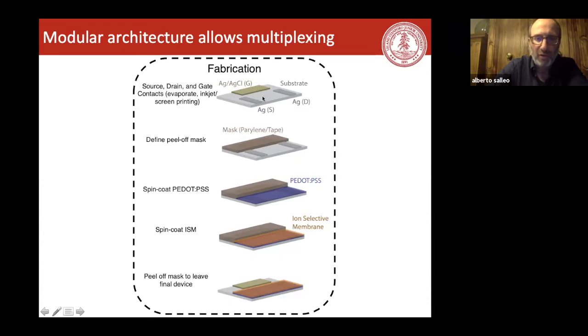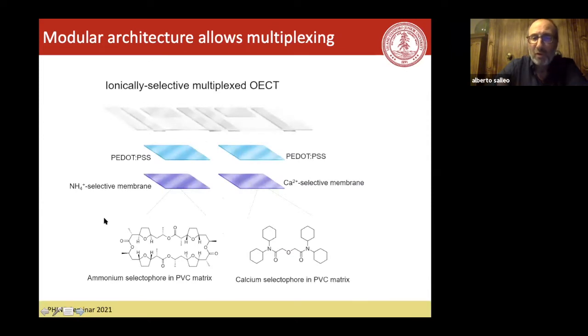This is a gate electrode. You deposit your polymer, you deposit your ion selective membrane, you unmask the silver chloride electrode, and now you can make this sensor very easily with very simple fabrication techniques. And because the device itself is always the same, it's always this transistor that has the PEDOT:PSS, this is a semiconductor, and then the two electrodes and the gate electrode. The only thing that makes different devices is the ion selective membrane.